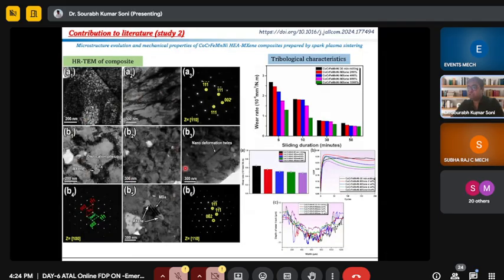This is the TEM. We must highlight the dislocation pileup or reinforcement particle present in our specimen, and some nano twins or stacking faults within the specimen, so that we can relate what is the reason behind the increment and decrement of the properties within the composites. So this kind of analysis we have to do for high impact factor publication.